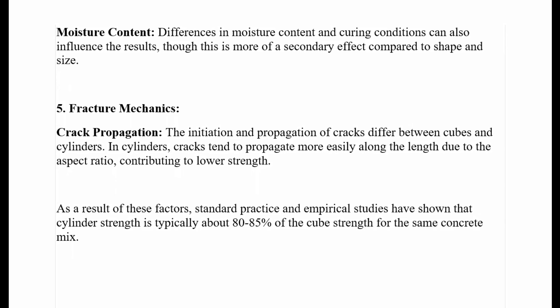Fracture mechanics — crack propagation: the initiation and propagation of cracks differ between cubes and cylinders. In cylinders, cracks tend to propagate more easily along the length due to the aspect ratio, contributing to lower strength. As a result of these factors, standard practice and empirical studies have shown that cylinder strength is typically about 80–85% of the cube strength for the same concrete mix.